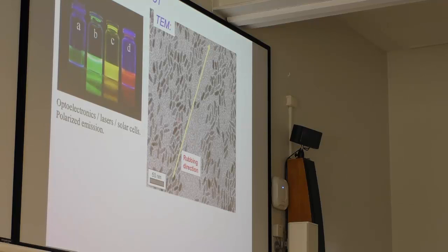You can also notice that some of these particles appear to be darker, and the reason for this is that this is TEM, and in TEM you have diffraction contrast, right? So those of these particles that happen to be oriented such that the diffraction condition is fulfilled will in this pattern appear to be darker, right? Because intensity will be diffracted out from the main beam.